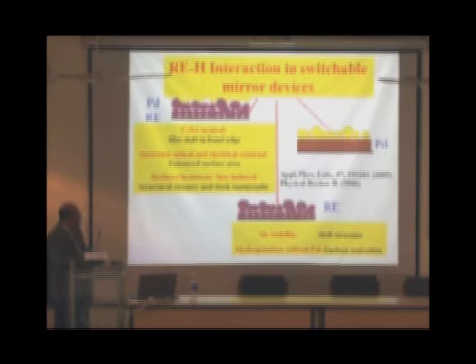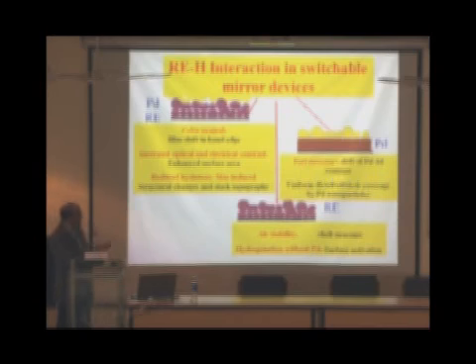So this was a very interesting effect, and it was possible to hydrogenate it, put hydrogen into the rare earth material and take it out, without the requirement of palladium, and some sort of surface activation is responsible. The presence of surface sites which convert molecules of hydrogen into atomic hydrogen hence does not require palladium. The third effect we investigated was changing the top layer of palladium from thin film to nanoparticles. So the hydrogen comes, it reacts with these nanoparticles, gets converted to atomic hydrogen, and that is what goes inside.